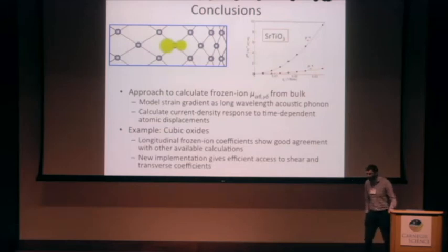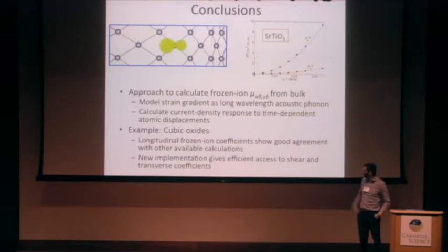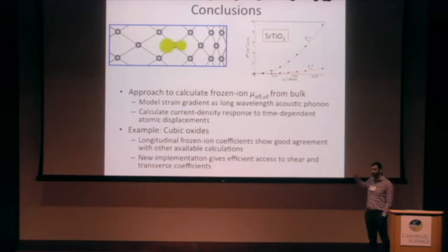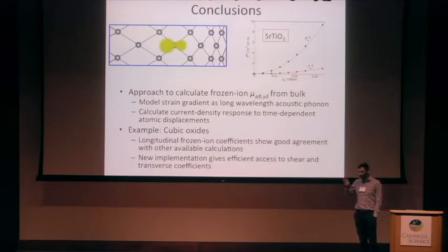Yeah, great question. So I didn't go into this, but in principle, if you're not careful, there'll be discontinuities of the polarization at Q equals 0 due exactly to this electrostatic boundary condition problem. So in the calculations I've shown, we enforce short circuit boundary conditions by, in reciprocal space, in these reciprocal space derivatives, removing the G equals 0 term in the electrostatic potential.